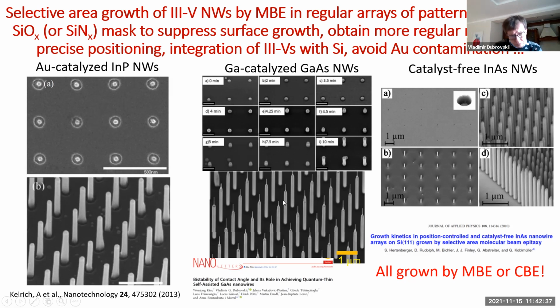Or you can grow III-V nanowires by a self-catalyzed approach, by pre-depositing gallium into the pinholes in silicon oxide, or you can grow them without any droplets at all in the purely selective area growth approach, where the pinholes direct the nanowire growth without any droplets on top. And there have been publications showing that in some cases, the selective area growth and VLS growth can even coexist in one sample, depending on the size of the wire as well as growth conditions.